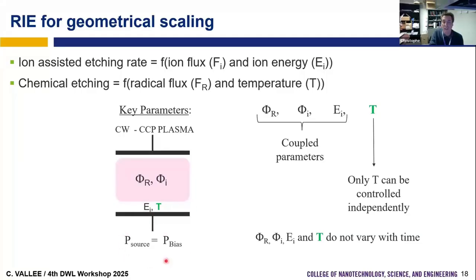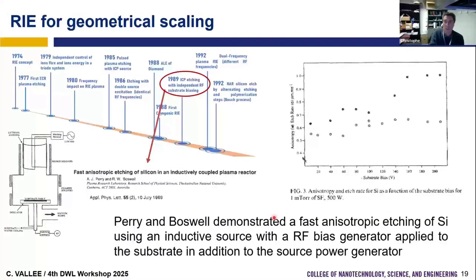Each time you modify the power applied to the substrate, if you increase the power, you increase the ion flux, but you also increase the ion energy. So it means that the parameters are coupled. You cannot only increase the ion flux without increasing the ion energy, or increase the ion energy at the same time as you decrease the ion flux. So all parameters are coupled, and all parameters will not vary with time. So from a processing point of view, to improve the capability of the process, maybe we could say, can we uncouple some parameters, or can we modify some parameters with time during the process?